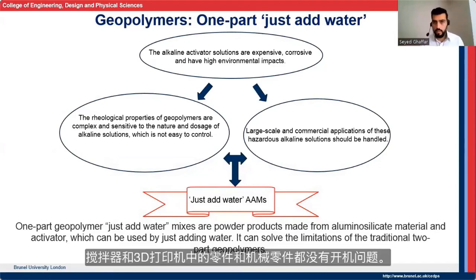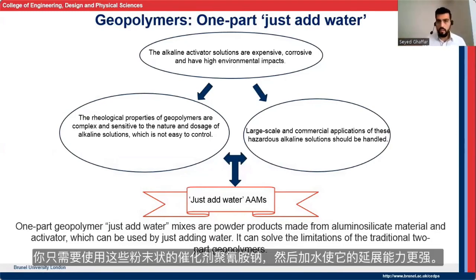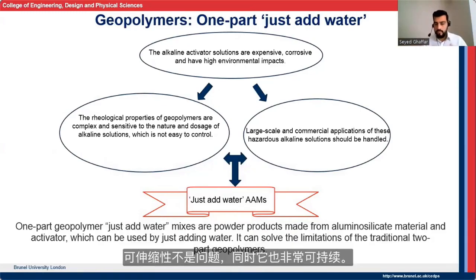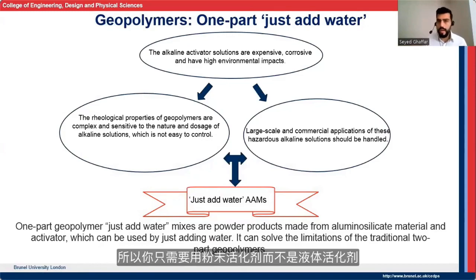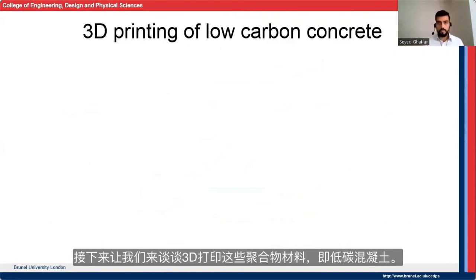And there are no wear and tear issues with the mechanical parts in the mixer or the 3D printer. You just use the powder form of these activators, sodium silicate, and you add water. So it's a lot more scalable. The scalability is not an issue, and it's very simple. At the same time, it's still very sustainable. So you just use a powder activator instead of a liquid activator solution.